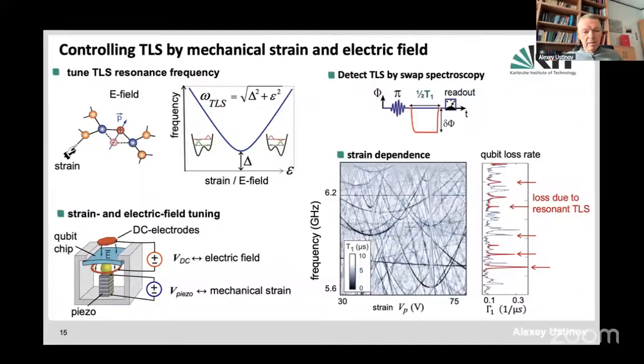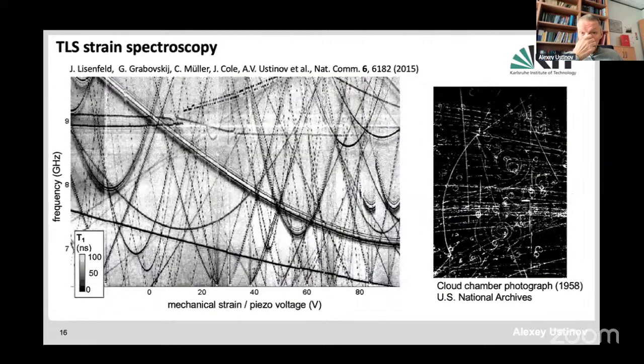But clearly, this type of plot is direct confirmation that these defects are two-level systems. They have a really textbook dependence of their frequency on a symmetry parameter. They have a random distribution of their gaps. And they also have different strengths of coupling to the qubit. So over the years, we have done a lot of studies of these defects, measuring their coherence rates as a function of frequency, measuring the interaction between them, and a lot of different things. I will show some of the citations here.